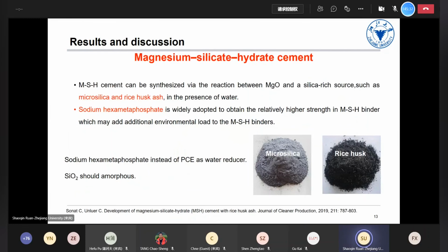Then is the magnesium silicate hydrate cement. Magnesium silicate hydrate cement can be synthesized by the reaction between MgO and a silica-rich source, such as microsilica and rice husk ash, in the presence of water. And sodium hexametaphosphate, instead of PCE, is used as a water reducer. However, when you use this water reducer, it may add additional environmental loads to the M-S-H binders.